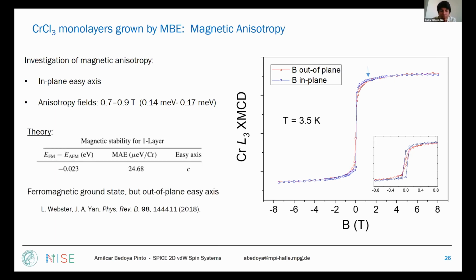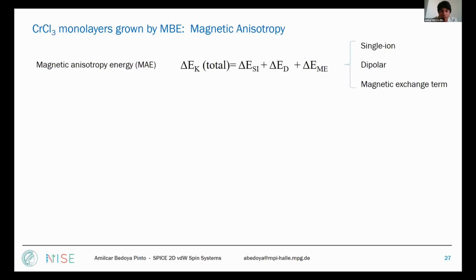So the theory, maybe I will skip this, just give you the reference, that says that some papers said that the easy axis would be even out of plane instead of in plane. So the anisotropy in the pristine chromium chloride treated by theory was so weak that even some people would say, oh, I'm not sure if it's in or out of plane. But in our case, it's very clear in-plane anisotropy with sizable anisotropy fields.